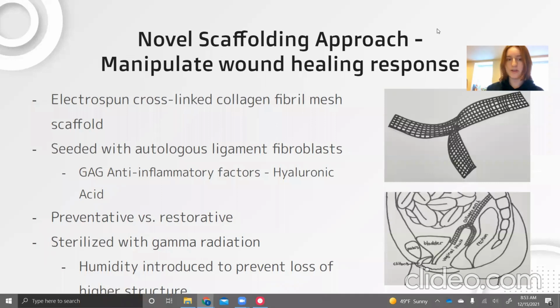To avoid these types of negative outcomes, our group proposes using an electrospun cross-linked collagen fibril mesh scaffold as a structural support. This scaffold would be seeded with autologous ligament fibroblasts, and the collagen would have glycosaminoglycans like hyaluronic acid introduced into it as an anti-inflammatory factor. This scaffold can either be a preventative measure or a restorative measure for already occurring POP.